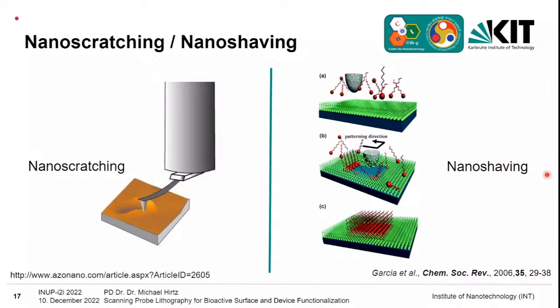And this is also already the first method that was used or exploited very early on, in particular this nano scratching, nano shaving approach. For nano scratching you can really think that you take a substrate, bring your tip to the surface, and press much harder than you would for imaging, so that the surface is exposed to a comparably large force, maybe in the nano to micronewton scale.